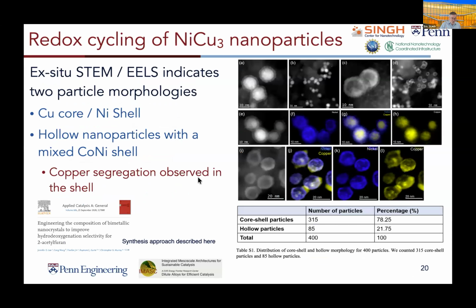So again, we went through and did characterization of the samples beforehand. It turned out that there were actually two types of samples present during the synthesis. In one case, we had core shell particles, where you had a copper core and a nickel shell on the outside, but in some cases, the particles were hollow. In this case, it was observed that there was copper segregated to the outer surface in these hollow particles. So by doing a large amount of imaging, we can get a reasonable understanding of the relative percentages of the different types of particles.